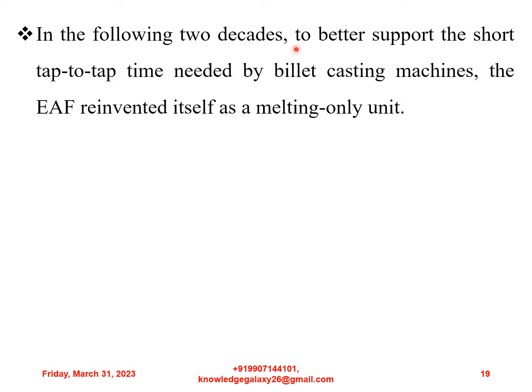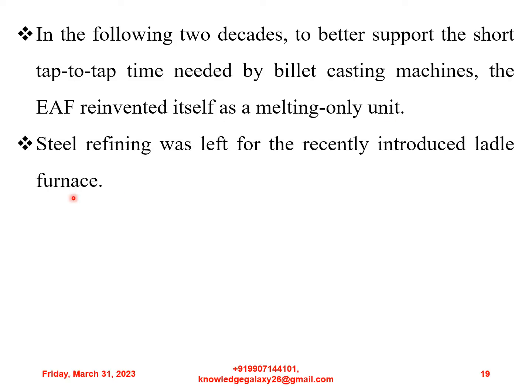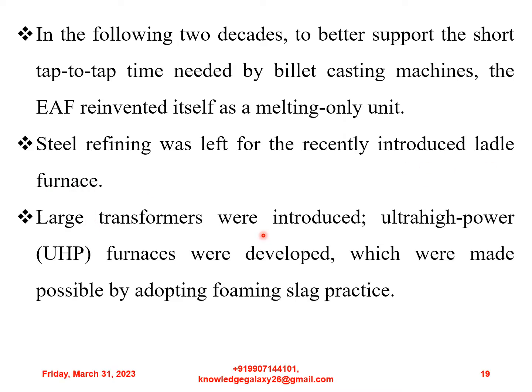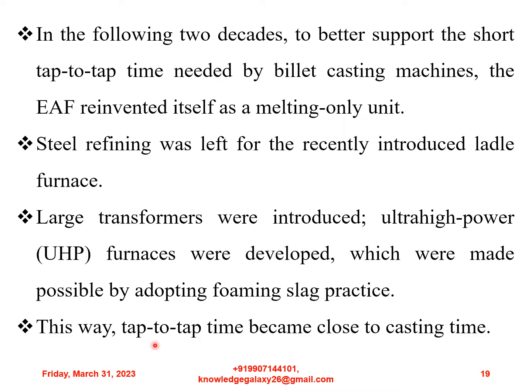In the following 2 decades, to better support the short tap-to-tap time needed by billet casting machines, the electric arc furnace reinvented itself as a melting-only unit. Steel refining was left for the recently introduced ladle furnace. Large transformers were introduced. Ultra-high power, that is UHP furnaces were developed, which were made possible by adopting foaming slag practice. This way, tap-to-tap time became close to casting time.